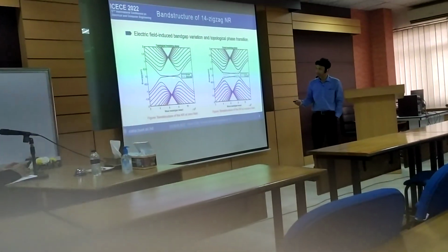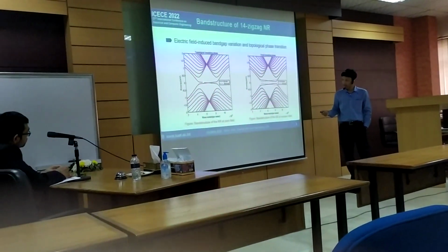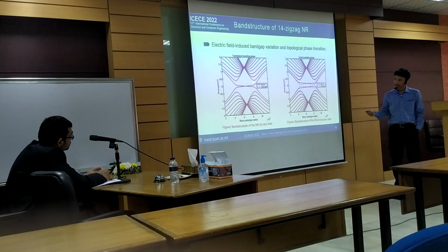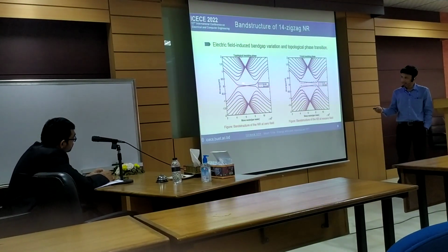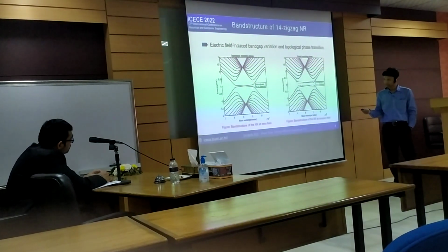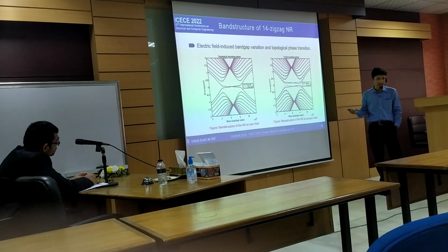So now you can see this basically represents the electronic properties. This represents the band structure of this stanene, for the on state. And just in the center here you can see the corresponding connection in the band, at K and K prime in the Brillouin zone. This is basically the signature of the topological insulating state. But you can see the two overlapping versions, that is from the upspin and the downspin carriers.